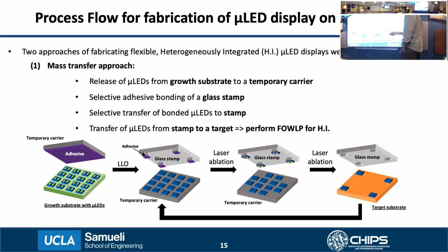So the leftmost is essentially you have these prefabricated LEDs sitting on a certain growth substrate, onto which you bond this temporary carrier and then do a process called laser liftoff that essentially releases the devices face down onto this temporary carrier. And then you use a glass stamp with adhesive on it, which you align and bond, and then pick up the devices, which is shown in the middle step, and then finally transfer them to the target substrate. The glass stamp can then be taken, cleaned, and then reused again in the next cycle of printing. So this is how a typical mass transfer process would look like.